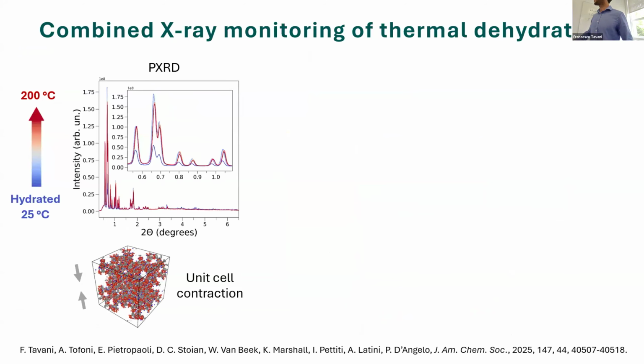So, let's look at the thermal activation of the MOF. Let me take a step back. What we did is we first thermally activated the MOF. We then brought it back down to room temperature and exposed it to water vapor. And then we followed the thermal dehydration of the fully hydrated MOF. So this is what we are following here.